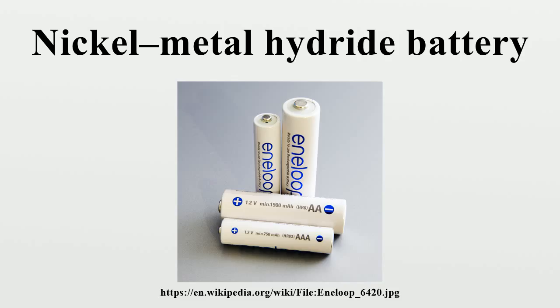Thick separators are one way to reduce self-discharge, but take up space and reduce capacity, while thin separators tend to raise the self-discharge rate. Some batteries may have overcome this trade-off using thin separators with more precise manufacturing and by using a more advanced sulfonated polyolefin separator. Low self-discharge cells have lower capacity than standard NiMH cells because of the separator's larger volume. The highest capacity low self-discharge AA cells have 2000 to 2600 mAh capacity and AAA 1000 mAh, compared to 2800 mAh and 1300 mAh for high capacity AA and AAA NiMH cells.